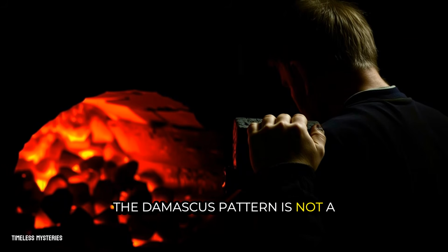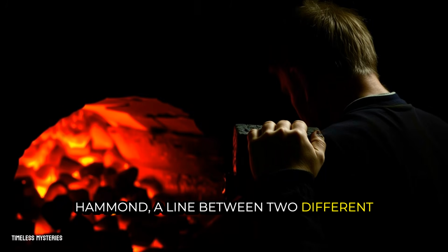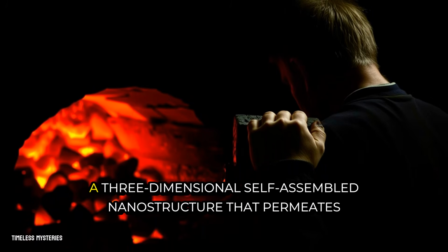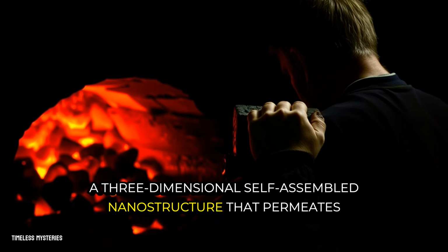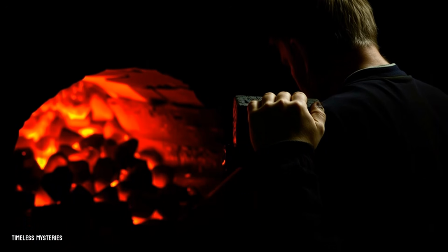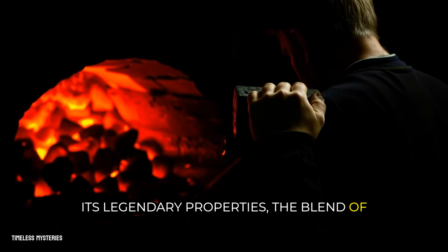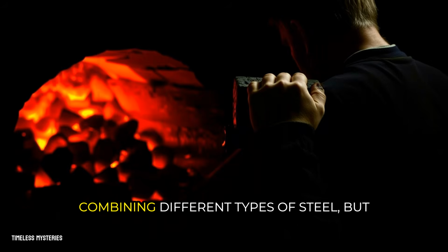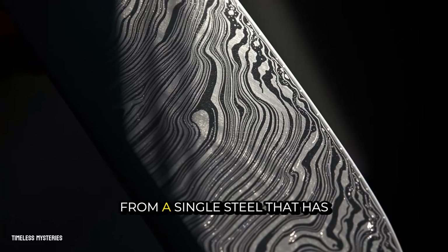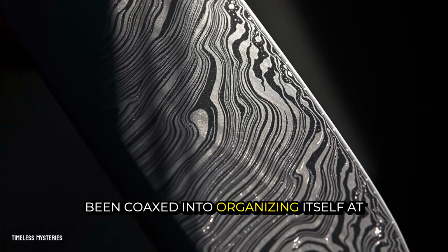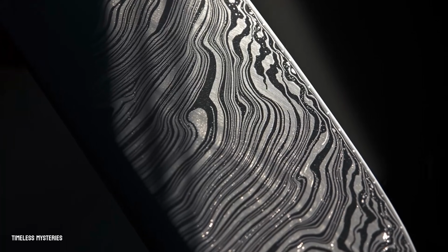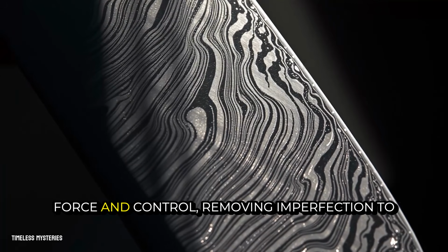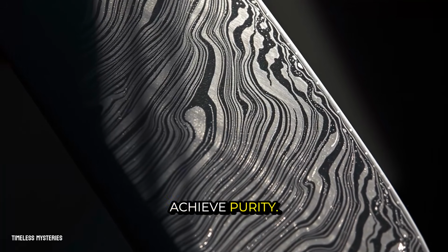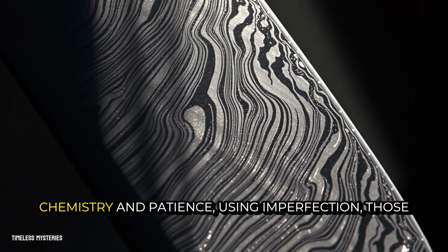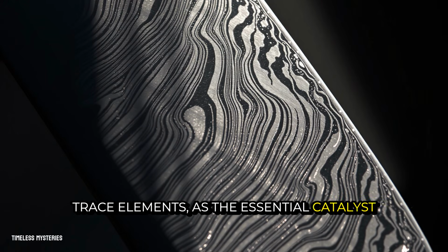The Damascus pattern is not a hamon, a line between two different zones. It is the surface expression of a three-dimensional, self-assembled nanostructure that permeates the entire blade. Its legendary properties, the blend of hardness and toughness, come not from combining different types of steel, but from a single steel that has been coaxed into organizing itself at the atomic level. One tradition is a symphony of force and control, removing imperfection to achieve purity. The other is a symphony of chemistry and patience, using imperfection, those trace elements, as the essential catalyst for growth.